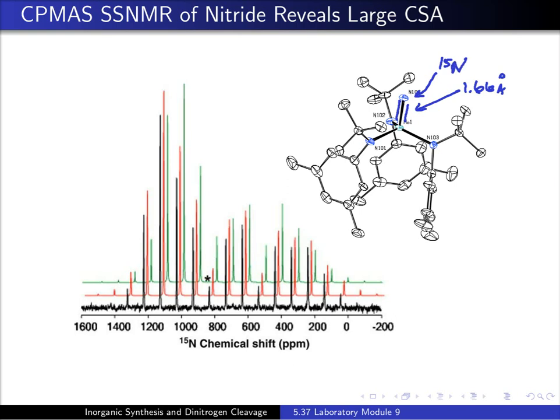And when we synthesize this with N15 labeling in the nitride position at the molybdenum nitrogen triple bond, we're able to get electronic structure information and characterize the nature of the molybdenum nitrogen triple bond by doing solid state NMR spectroscopy, N15 NMR spectroscopy, in conjunction with quantum chemical calculations that have allowed us to simulate the experimentally derived spectrum. So the green spectrum, which is offset, is from quantum chemical calculations. The predictions not only of the isotropic chemical shift, that is the average shielding for the nitrogen if it were tumbling, designated here by the asterisk, about the chemical shift comes at greater than 800 parts per million. Here's the isotropic chemical shift.